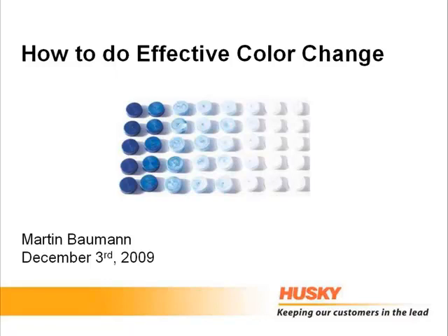There's a good question in regards to purging the hot runner with the mold gates open. We do not recommend that for safety reasons. And also typically on most injection molding machines, when the gate and mold is open, you cannot use your full injection speed or your full injection pressure. And as I demonstrated during the presentation, shear rate is actually very important for fast color change. Because you're slowing down the system, you won't get the benefit of that increased shear rate. So we don't recommend doing it this way. The best way is molding full parts at increased injection speed and pressure, not at decreased.